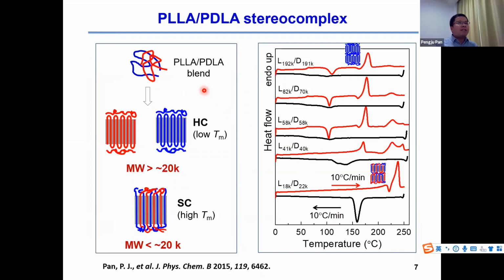Unfortunately, not all PLLA and PDLA blends can easily form the stereocomplex crystal. In the crystallization process of the PLLA and PDLA mixture, there is a competition between two crystallization processes. One is the homocrystallization of PLLA or PDLA. The other one is the co-crystallization between PLLA and PDLA. We have found the molecular weight is a key factor for these two crystallization processes. Low molecular weight PLLA and PDLA have a fast crystallization rate and mainly form the stereocomplex in the common cooling and heating process. However, when the molecular weight of PLLA and PDLA is higher than 20,000, the blend mainly forms the homocrystal in the cooling and heating process. The crystallinity of stereocomplex is very low.